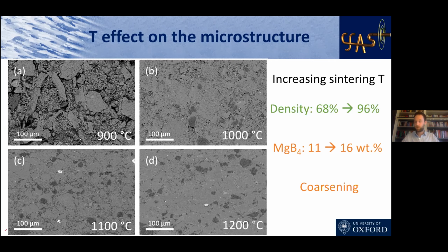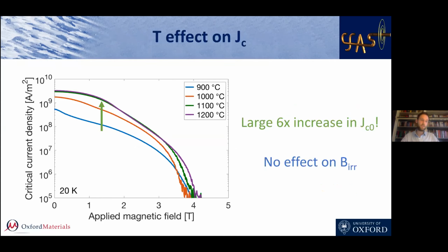How did that influence the properties? Well, here's the critical current density of those 4 samples. And the main thing is that we saw a very large increase, a 6-fold increase in JC, and in particular in JC at low field. But you can see for the purple curve that this improvement is pretty much on the whole field range. And then we had no effect on the irreversibility field. So it was actually quite a positive result, because even though we had a bit more MgB4 and we had some coarsening, what played in favor was just the huge increase in density.